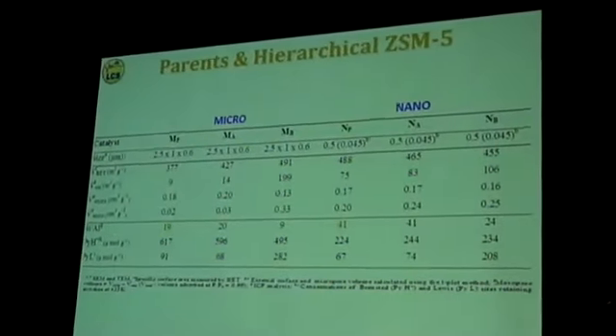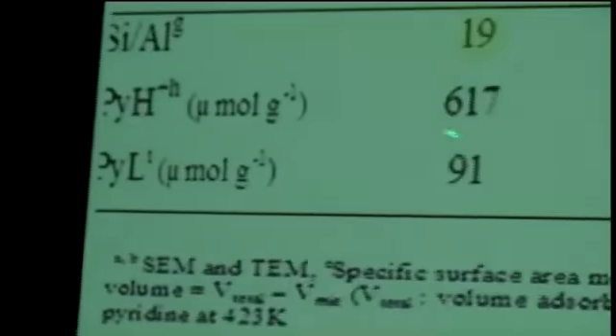What you see also here is that the number of Bronsted sites, which are the active sites in this reaction, is relatively high on the starting material. Of course, it's lower here on the nano-sized material because the silicon to aluminum ratio is different.